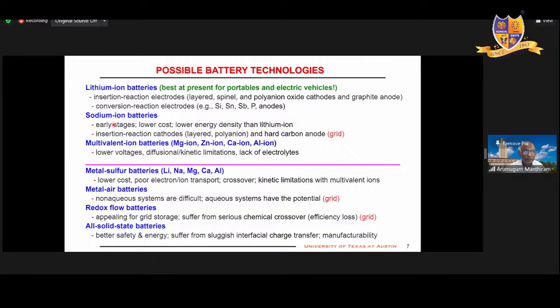So by having good characterization, we have an understanding of the dynamics, what is going on between the electrode surface and the electrolyte, the liquid electrolyte reaction. So that has helped us a lot to learn. So, okay, you have a problem, you are telling us the problem, how are you going to fix it? The same problematic material, you put 2% aluminum, then the cyclability becomes better, the voltage stability becomes better, because as soon as you put aluminum, metal dissolution is decreased. These transition metals dissolve, they go from the cathode to the anode, and they mess around the graphite anode. When we put aluminum, that is decreased, that's why you get better performance.